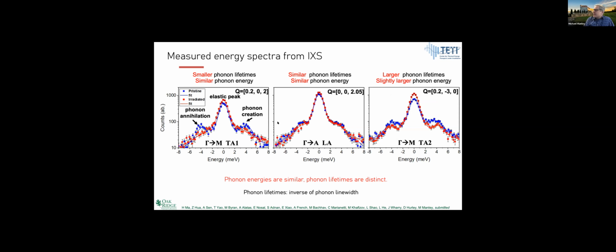So it's interesting. It's sort of a complicated thing. If you look in certain parts of reciprocal space, particularly in the middle parts of zones, like this one at 0.202, it's a transverse phonon along gamma to M. It's sort of in the middle, and there you see a pretty large broadening with the irradiated sample compared to the pristine sample. The irradiated is the red, on the left, and the pristine is blue. Whereas if you go towards the zone center, the longer wavelengths, you don't see as much. So whatever the defects that we're forming, which I'll talk about in a moment, are not affecting these phonons so much. And then at some of the zone boundaries, you actually see a little bit of sharpening. So it's a rather complicated thing, and the structure that occurs is fairly complicated.